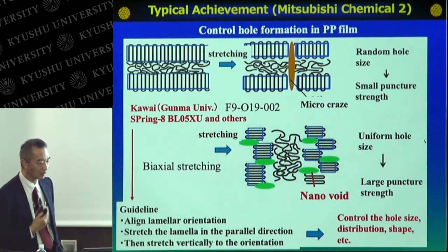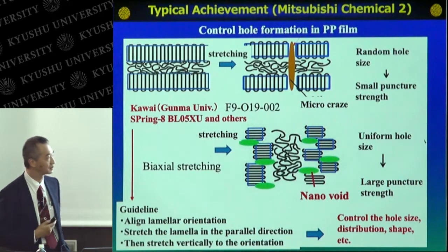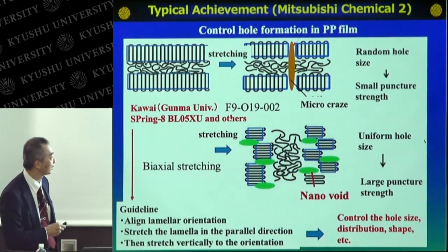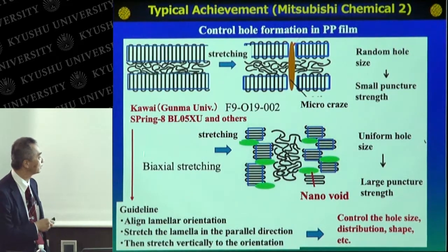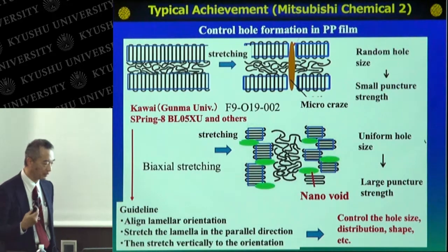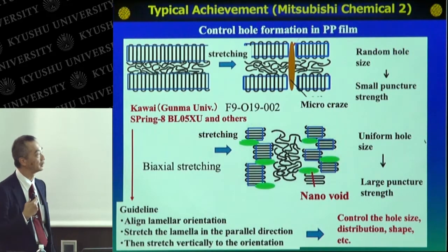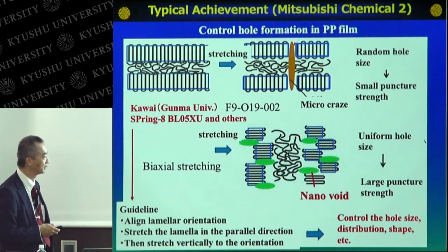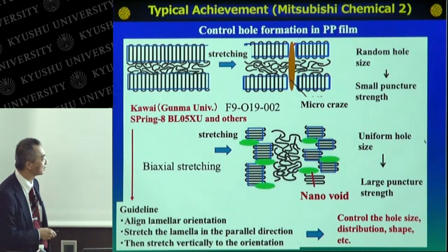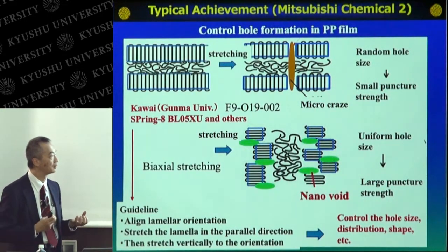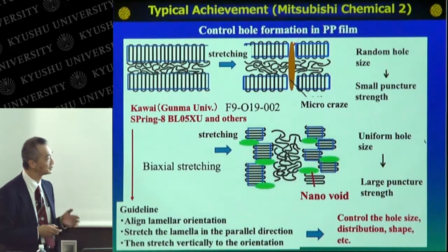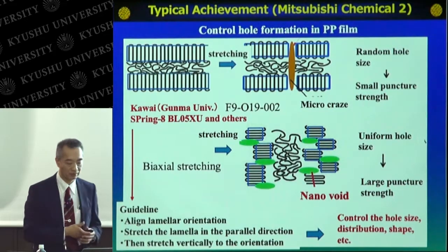So Professor Kawai and Mitsubishi Chemical clarified the mechanism of void forming in the polypropylene films. Finally, they obtained the guideline to create very uniform nanovoids and control the hole size and distribution. First, they aligned the lamella orientation in the polypropylene film, and they stretched in the parallel direction to the lamella first, and then they stretched vertically to the lamella direction. Then they can obtain the voids, nanoholes, in the polypropylene resin. So finally, they can control the hole size, hole distribution, and hole shapes.